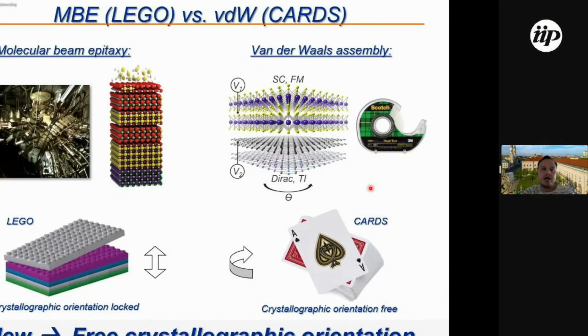I want to contrast this with what was done years before van der Waals heterostructures. Since the 70s, heterostructures of semiconductors or complex oxides were a famous topic. Over the years people learned, in a very complicated manner, how to grow layers of different materials repeatedly one on top of another. But with those techniques, people start with a single atom. They had to sprinkle atom by atom on the surfaces, and this had the limitation that all the individual atoms would assemble in the same crystallographic orientation as the parent material. So creating twist angles between the crystallographic lattices of the heterostructures was not feasible with these growth techniques. This is entirely different in van der Waals materials, because we start with preformed two-dimensional lattices. We have this tuning knob and control of the crystallographic orientation.